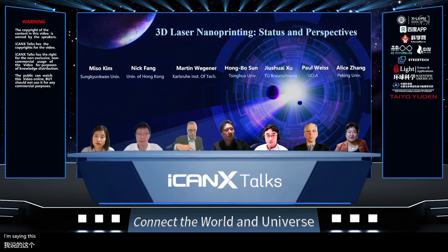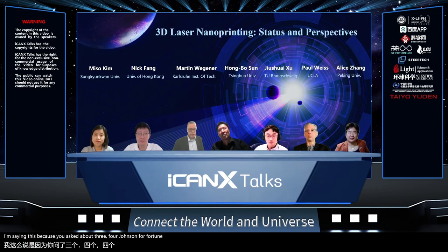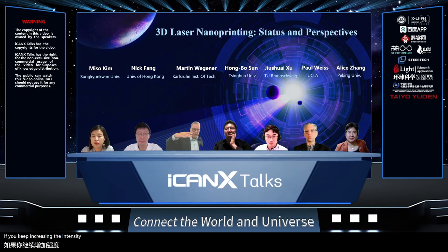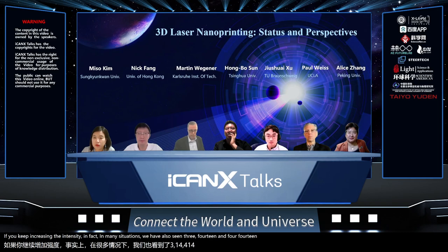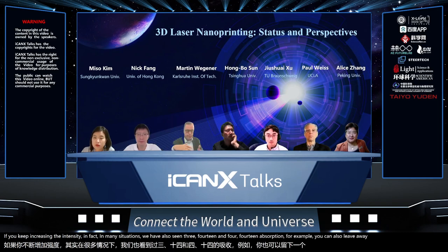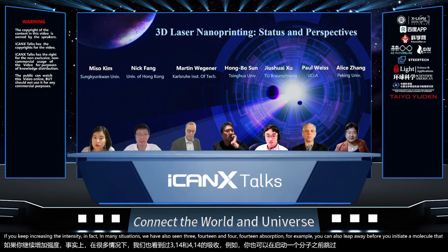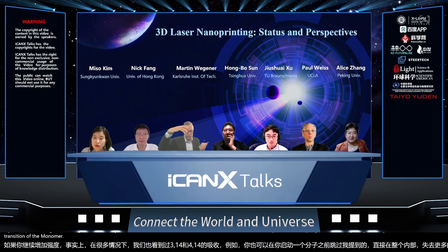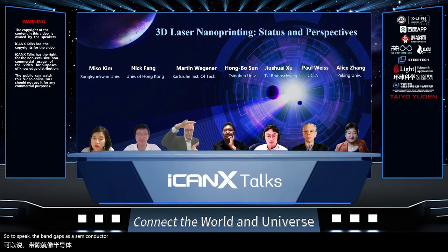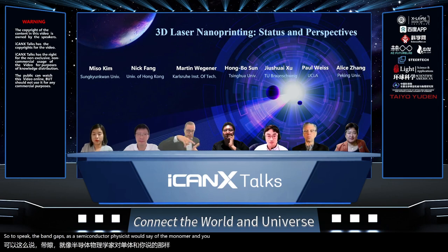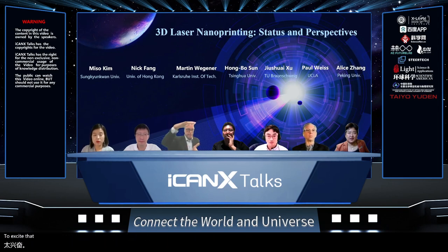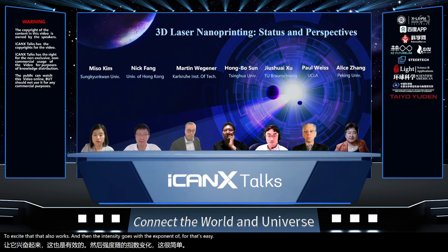I'm saying this because you asked about three photons and four photons. If you keep increasing the intensity, in many situations we have also seen three photon and four photon absorption. For example, you can leave away the photoinitiator molecule that I mentioned and directly excite the HOMO to LUMO transition of the monomer. So to speak, the band gap, as a semiconductor physicist would say, of the monomer, and you take four photons to excite that. That also works. Then the intensity goes with the exponent of four. And that's even better because you get rid of the tails of the laser focus even better.